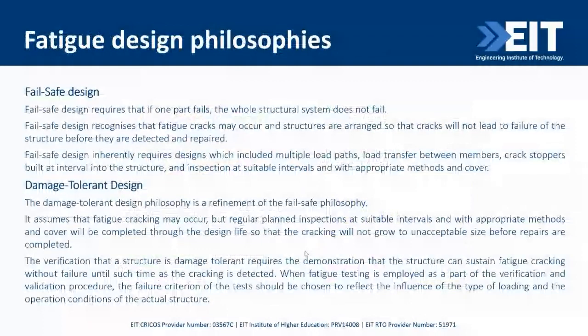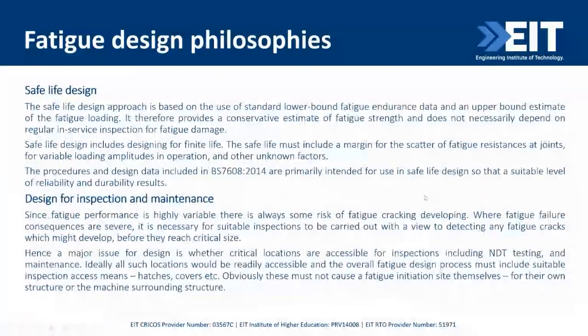That's the first lot. Damage tolerant is a refinement, but it includes regular inspections. Go through that at your leisure. Safe life design is what BS 7608 and most of the fatigue codes are based on. So you're looking for safe life design, so the suitable reliability and durability results, because you're using an upper bound estimate of the fatigue loading. So you're being conservative on the fatigue loading, and you're using lower bound fatigue endurance data, so you're conservative on that as well.